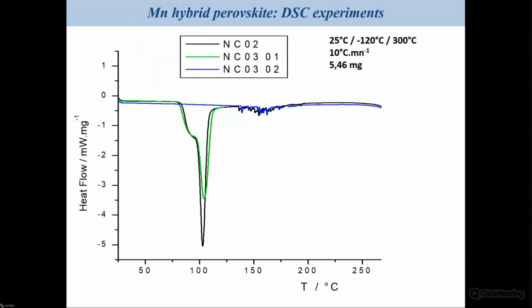What is interesting in the system is that if you make a DSC experiment, you see that you have different results depending on whether it's the first heating or the second or third heating. For the first heating, in black or in green in my graph, you see a very huge endothermic peak appearing around 100 Celsius degrees. But if you go down in temperature after the first heating and warm it again, you see that the blue curve didn't indicate such a behavior. So it means you have a transition which is not reversible in your system.